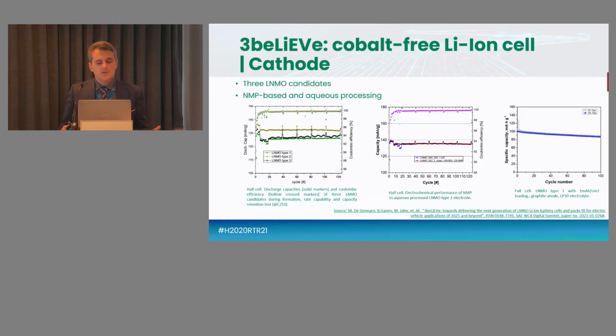The first slide here is about some interim results on the chemistry and the cobalt-free LNMO cathode. On the left-hand side of the slide, we see the earliest cycling results on the half-cell cathode. We did develop 3 types of LNMO that we have labeled as type 1, type 2, type 3. And what we can see is that we do achieve quite good cycling results. These results were presented also at the SAE World Congress last year. And we do achieve a capacity between 125 and 135 milliamp hour per gram at half cell level, which is quite close. It's around 80 to 90% of the theoretical capacity of 147 milliamp hour per gram. That's the maximum that is achievable by the chemistry itself.